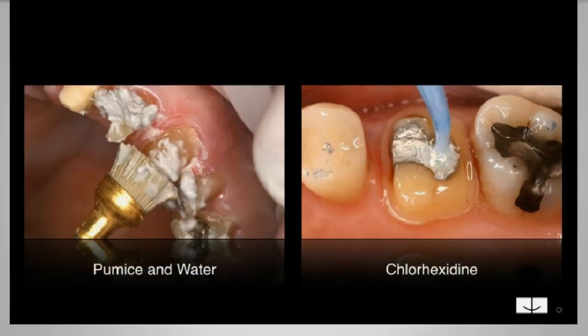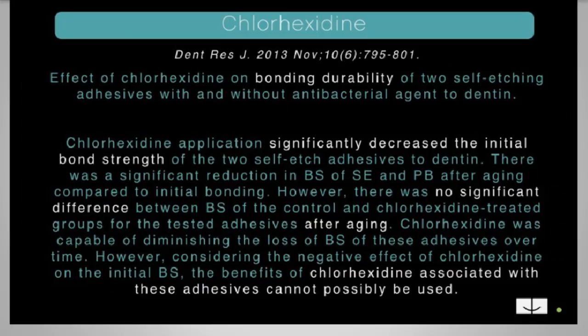But if you are using a self-etch adhesive, you have to be careful with the effects that chlorhexidine can have on your self-etch adhesives. There was this really interesting study that came out a couple years ago about the bond durability when using chlorhexidine with self-etching adhesives. Basically, they found that if you use chlorhexidine to clean off the preparation, or you could say if you were just in your regular composite restorations, right? If you use chlorhexidine before you used self-etch adhesive, you significantly decrease the initial bond strength.